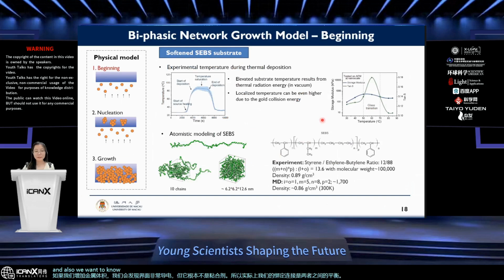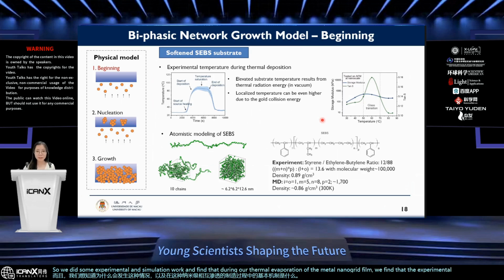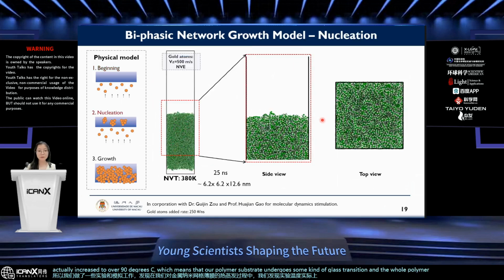And also, we want to know why it happens and what is the basic mechanism during the fabrication of such nanoscale interpenetration. So we did some experimental and simulation work and find that during our thermal evaporation of the metal nanogrid film, the experimental temperature actually increased to over 90 degrees C, which means that our polymer substrate undergoes some kind of glass transition, and the whole polymer becomes softer.